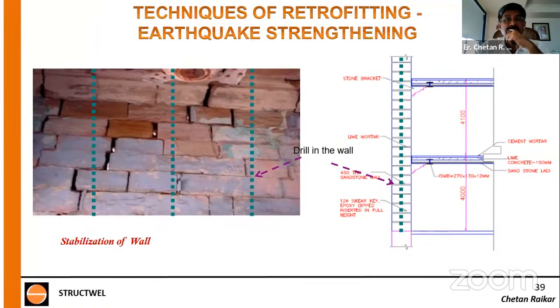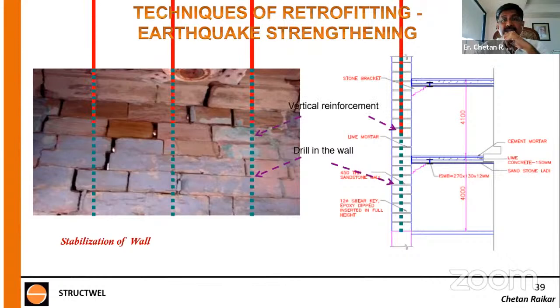drilled 50 mm dia, 2 inches, holes at 1.5 meter center to center in every wall and every T junction of all the walls, right from the terrace to down. So we did 50 mm dia hole of about 11 meters height from top into the plinth. Then we inserted a steel rod. Again, 12 meter long steel rod we inserted from top into the plinth, cut off the top portion.